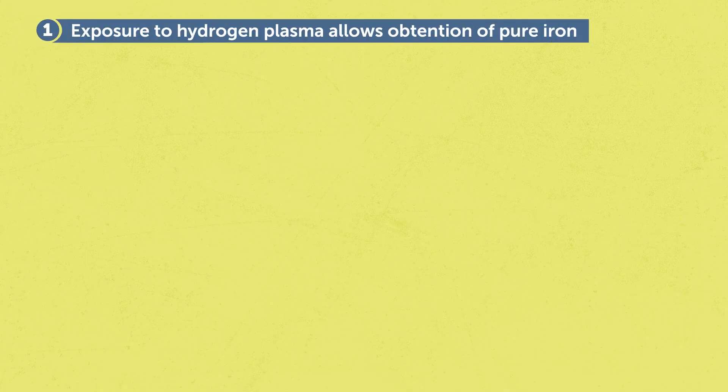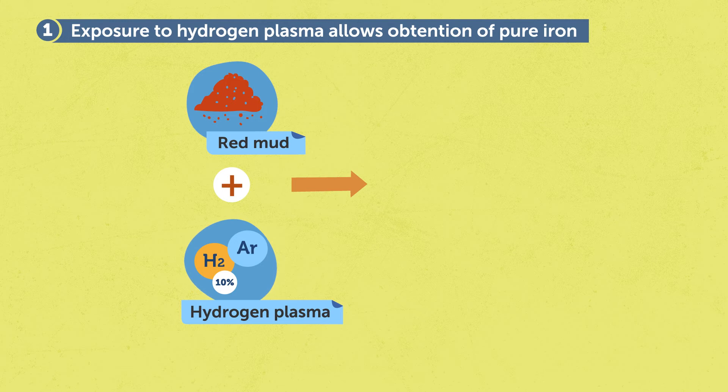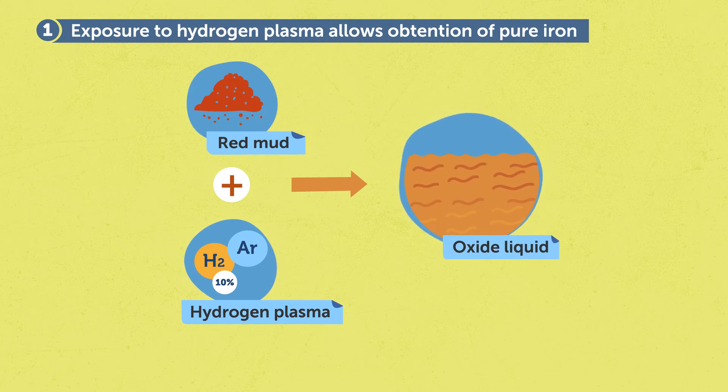The key findings of our research was that the direct exposure of solid red mud to a hydrogen plasma allowed us to transform the solid material into a very viscous oxide liquid. Inside this viscous liquid,